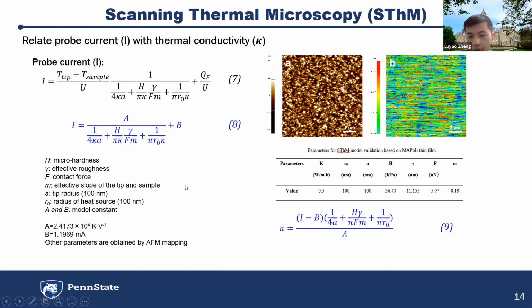First we validated the setup by measuring some well-known perovskite materials, the typical MA lead iodide. The value we got is about 0.5, which is consistent with some literature reports, indicating our model is suitable for perovskite materials. And we rewrote this equation into this figure version. Then we can directly obtain the thermal conductivity by measuring the probe current during the mapping.